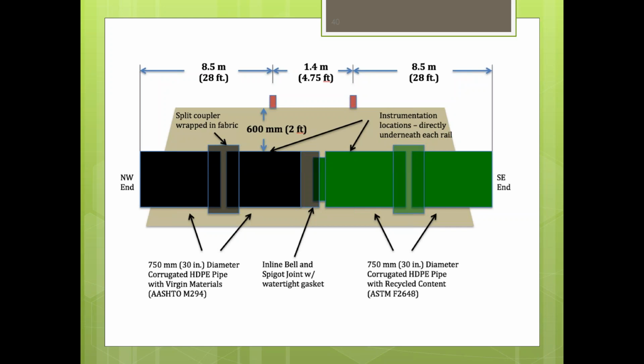As a funny side story and note, typically their standards don't allow any pipe to be within, I believe, 6 feet of the bottom of the rail. So when they showed up on site to install these pipes, there was actually an expectation that it was going to be much deeper. But because of circumstances on the project, they were able to install them with only 2 feet of cover, which really gave us much higher quality data from a live loading standpoint and a dynamic loading standpoint to analyze and take a look at.